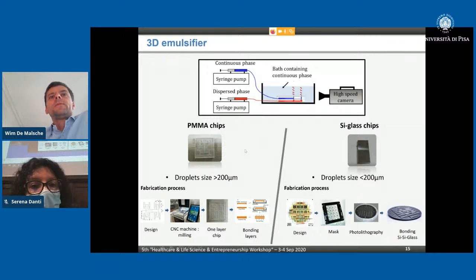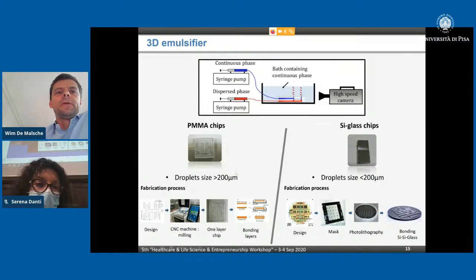We are working on two types of substrates. One of them is plastics, and these are typically PMMA, but also cycloolefin copolymer. These we are milling with our milling robot. This is very cheap. The only problem is we are a bit limited in the size of the nozzles, and so of the droplets. But typically, for many of the chemical applications we are performing, this is a very relevant size. Also, for many of the applications, the droplets shrink afterwards. They can still shrink tenfold, and then we can end up with 20 micron particles still. And that's a very relevant size for many applications.